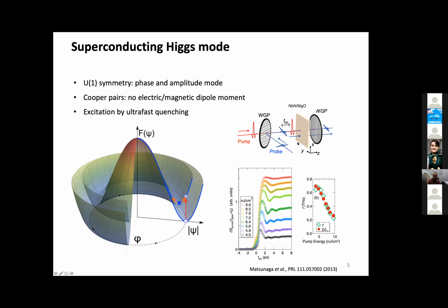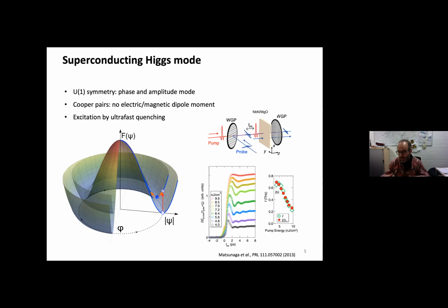And what they did, they were exciting the system with an ultrashort terahertz pulse. This terahertz pulse makes sure that you quench this condensate without exciting hot quasiparticles that would screen the response. And then they were probing this response with a time delayed terahertz pulse. And then they found here some characteristic oscillations after this quench of the potential. And then depending on the strength of this quench, so with increasing fluence, they quench this potential more and more. And what they see then is that this oscillation gets slower and slower. And they could show that this oscillation is always following this transient size of the gap of 2 delta. And that was the first fingerprint for a Higgs mode oscillation that was excited in a superconductor.